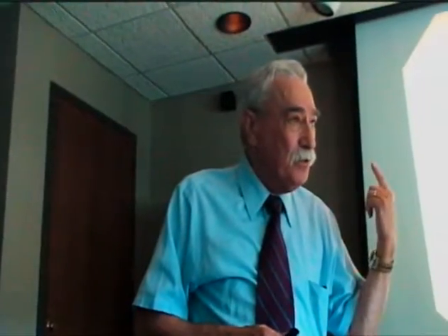However, I just mentioned at lunch that my student Jane Huang found a solution to how to make this stuff porous. It was very simple. She put twice the amount of zirconium in that stoichiometry would tell you. She heated it at a low temperature hydrothermally, like 80 degrees, and wouldn't you know, it comes out with 400 square meters per gram and regular pores. Now, ask yourself why. Well, the point is, we really don't know why yet.